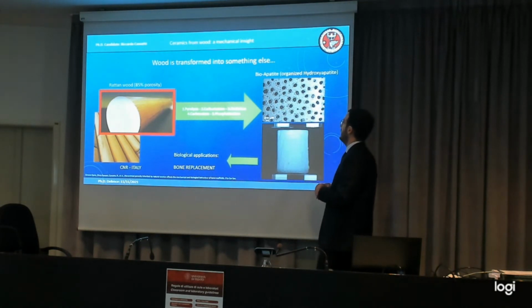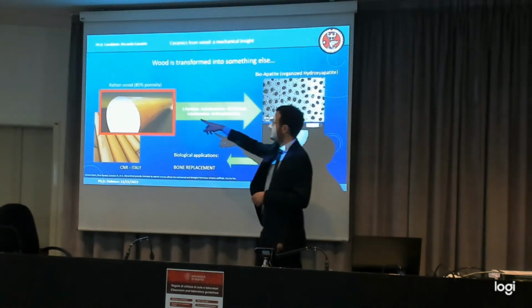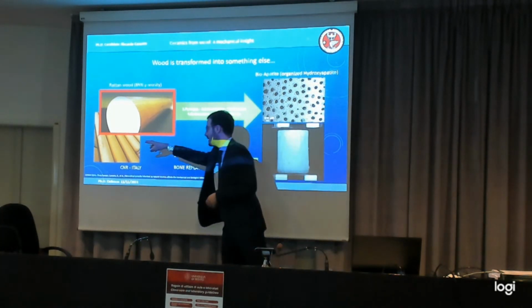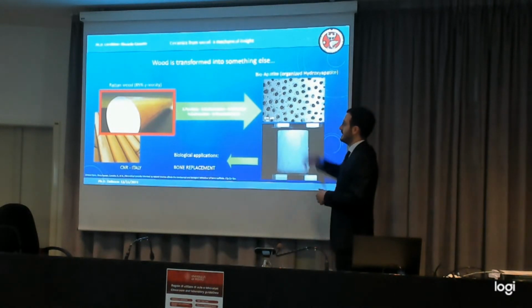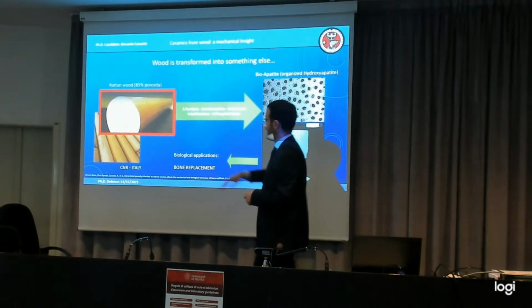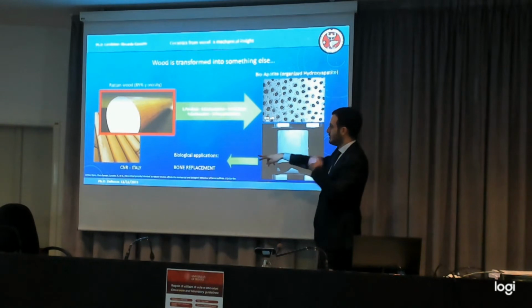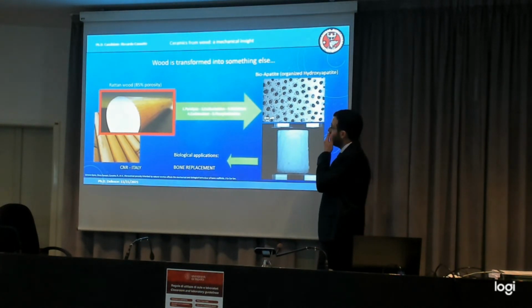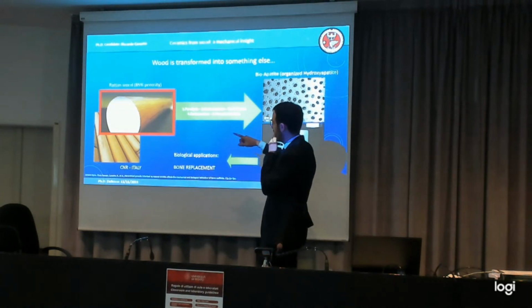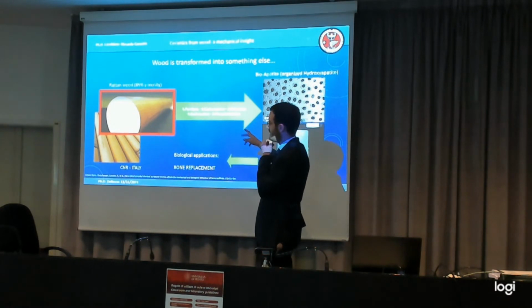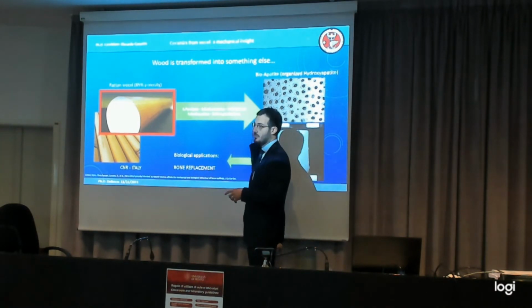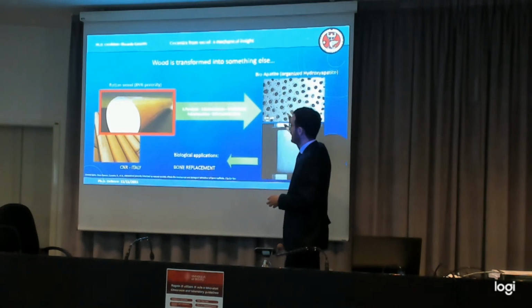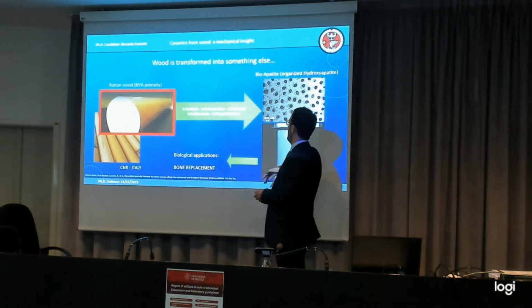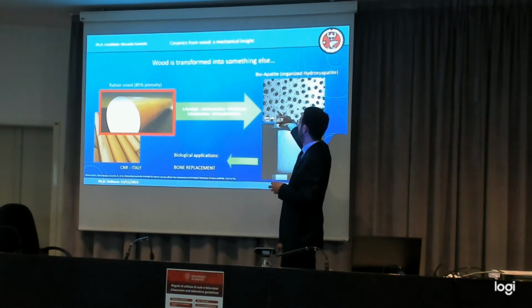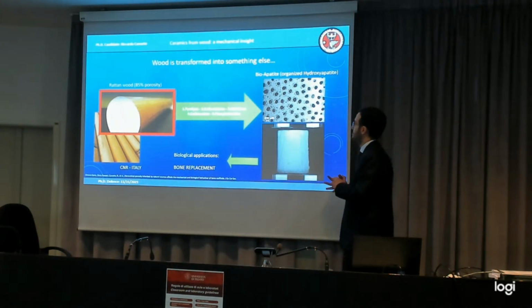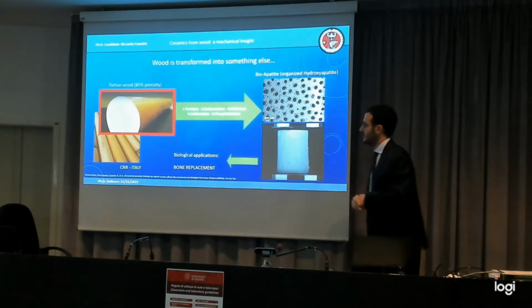And I want to talk about this bioapatite material, which is an organized hydroxyapatite obtained from rattan wood through a series of chemical processes that transform the wood into an oriented hydroxyapatite ceramic. The reason why CNR developed this material is because it is sought for bone replacement applications, so in biomedicine, and by performing this type of transformation, they were able to avoid the sintering process. Sintering processes are high temperature and pressure processes that destroy the biocompatibility of structures. So they were able to produce something that was extremely biocompatible. We've seen it. It is extremely biocompatible, and that is due to the different levels of porosity shown in the microstructure.